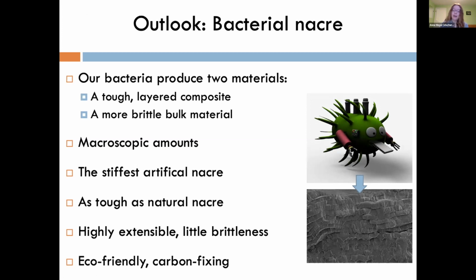Even though our nacre is not as stiff, we're like 10-fold less stiff than natural nacre, it's still the stiffest artificial nacre ever produced, which I think is a great milestone. It's exciting that it's as tough as natural nacre, because that's the famous property that everyone wants to replicate. It's exciting that it's highly extensible. You can bend it very far without it being brittle.